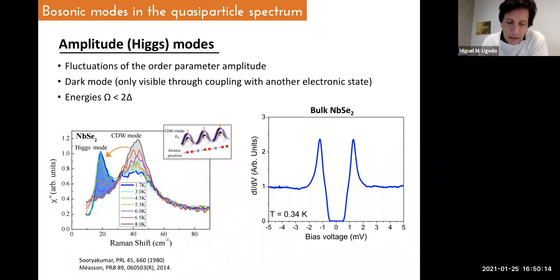The reason is that the system becomes superconducting but also coexists with a charge density wave mode, and that allows this dark mode to emerge and become visible. As you can see, this energy is around 1 point something millielectron volts, so it could be compatible with what we see. The problem is that we see nothing in bulk.